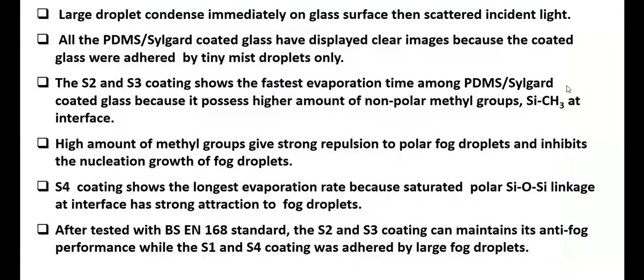It's more than half, and this is due to the hydrophobicity of the coating system. So this is what has been cleared over here. The bare glass substrate possesses a blurry image due to the addition of large droplets. The large droplets condense immediately on the glass surface, then scatter the incident light. All the PDMS/Sylgard coated samples displayed clear images because the coated glass was adhered by tiny mist droplets only.